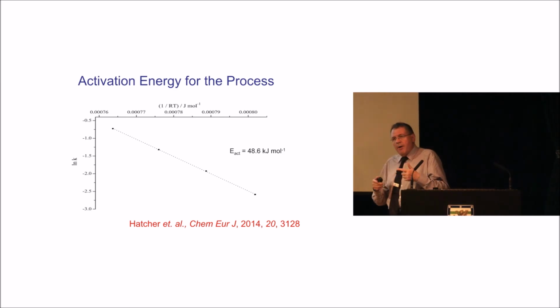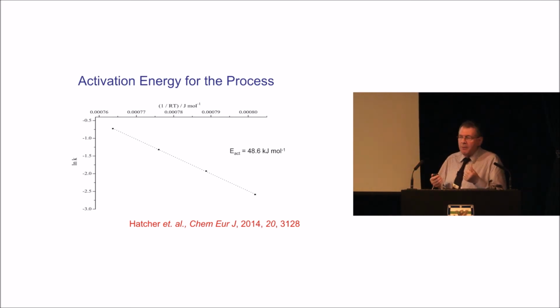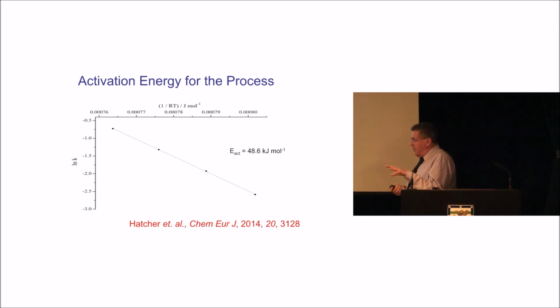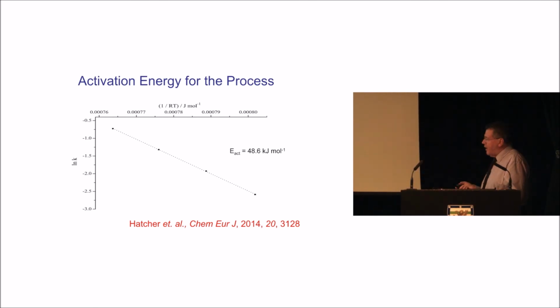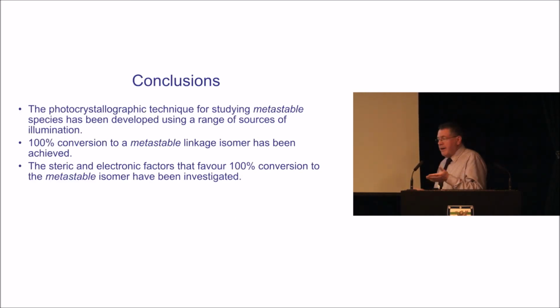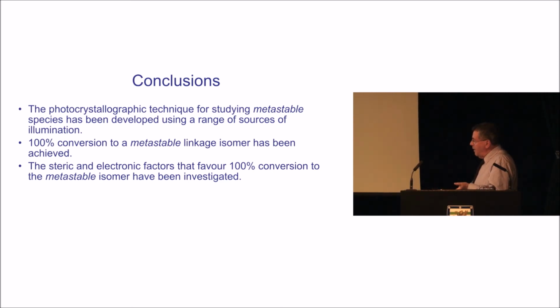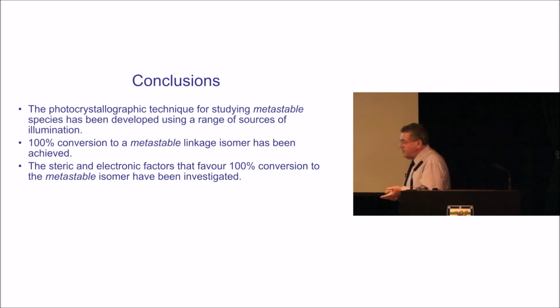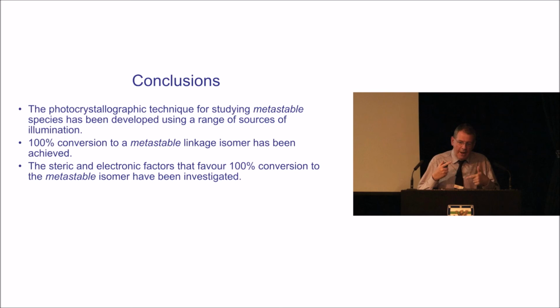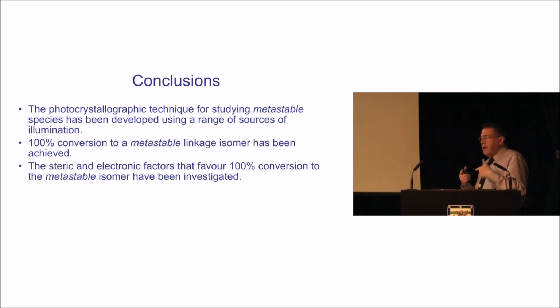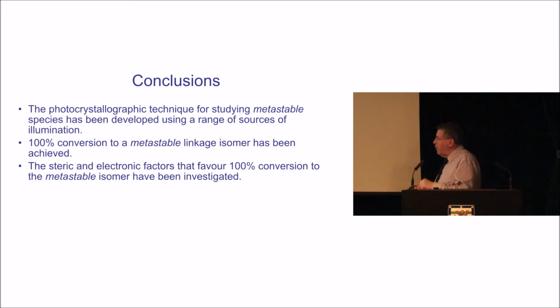So that's pretty well where we are in trying to design these systems, but I would like to emphasize that the CSD is fundamental in all this. We always use that to look at the likely molecules that will transform and the cavities and the energetics in these systems, and I'm sure that's going to be a very important use of the CSD in the future. So just to summarize, we've developed the technique that allows us to look at these metastable systems. We've got the first 100% conversions on these materials, and I think what we've established is that both steric factors are probably most important, but there are also kinetic factors that we have to consider when looking at these transformations.